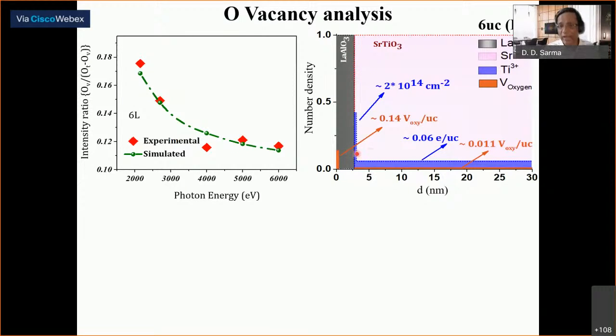donations. And this is not in contradiction to the polar catastrophe model, in the sense that the fact that these oxygen vacancies donate the electrons here has something in common with what is presupposed in the polar catastrophe model. So basically, the system undergoes, after transferring the electrons here, because the electrons go out from the bonding level of the lanthanum aluminate, and therefore some oxygens become unstable and leave the surface, and therefore there's no charge imbalance. And the lanthanum aluminate surface is not expected to be then metallic because of hole doping.